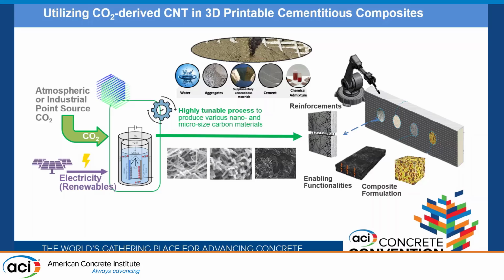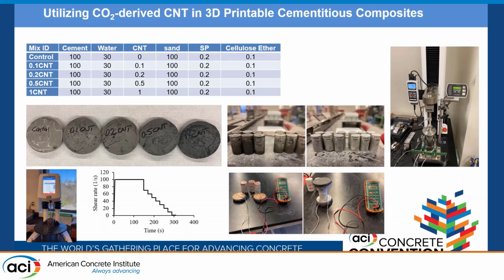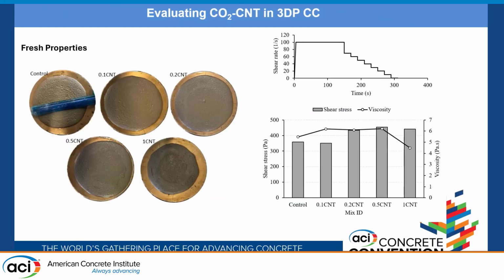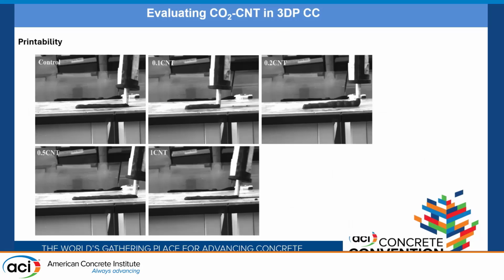Previously, the CNT morphology was very much like CVD-produced CNT, but in this case, since we're doing it for 3D printing, we communicated with Sky Nano, saying we want your largest sample size, which I think was a mistake, but I'll show you in a second why. And so we basically made those mixtures, and we ran all different kinds of studies, from the rheological properties onward. As you can see, as we added a dosage of CNT, the shear stress started to increase and decrease. There's not a significant change in a lot of the results I'm showing here, and we wondered why it doesn't behave like a CNT, and that's what we later found out. It's not CNT that we mixed in.